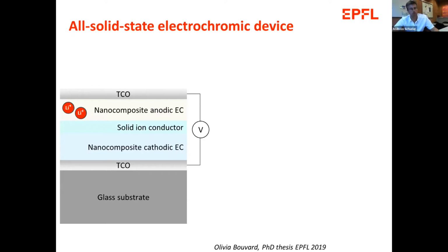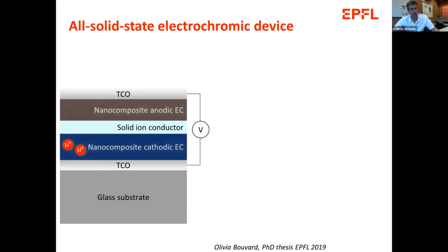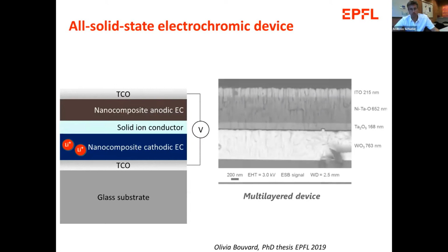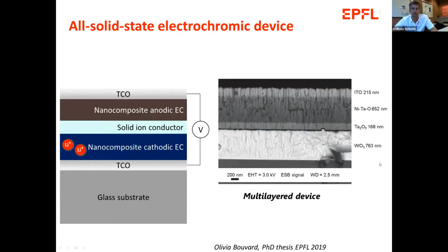So when we charge this battery, the lithium ions would migrate from the anode to the cathode, and both electrochromic layers would tint. Now, a device which has been made by our PhD student Olivia in our laboratory looks like this. So there is the cathodic electrochromic layer based on tungsten trioxide, then tantalum oxide as a solid ion conductor, and the counter electrode is based on nickel tantalum oxide. And there is the top layer of indium tin oxide.